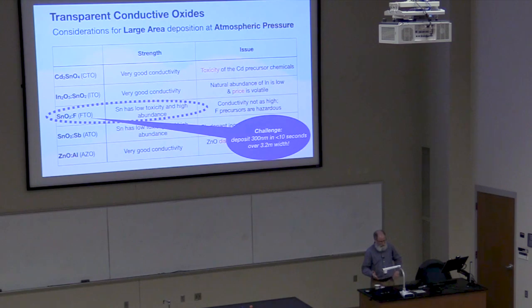So then the challenge is, can we make 300 nanometers, which is what we needed for sheet resistance, in less than 10 seconds? Because the glass speed is fixed. They're not going to slow down the glass for us to coat it. You've got to coat it. Here's your space, here's your time, make it work.